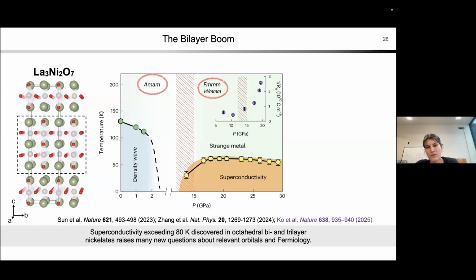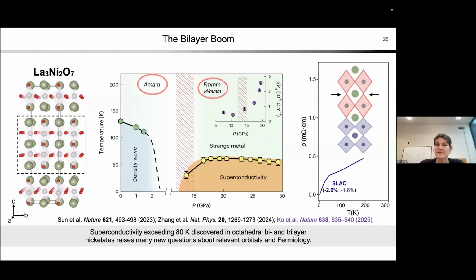So we can't really do electron microscopy under high pressure conditions at this point. But what we can do is work again on thin films with that strain that I told you about. And so some of our collaborators were able to show that instead of using high pressure, you can actually use the substrate to push on the lattice, and you can again stabilize superconductivity that you're seeing here down in this trace on the bottom. So that's where we got very interested, and we thought, okay, this is something we can put in the electron microscope and we can understand what's going on at the atomic scale.